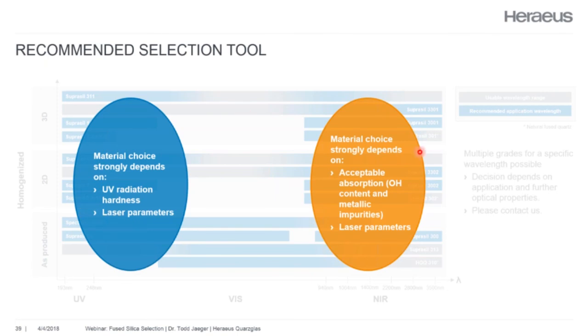And then on the other side of the spectrum, on the near infrared, the material choice is going to depend on what's acceptable for absorption, right? How much OH content can you have? What level of metallic impurities can you have? This is going to determine whether you'll go with a fused quartz or a fused silica, and whether you're going to go with a Suprasil 311 that has OH content less than 300 ppm, or you're going to go for a 3001 that has the OH content of less than 1 ppm. And of course, consider the laser parameters.